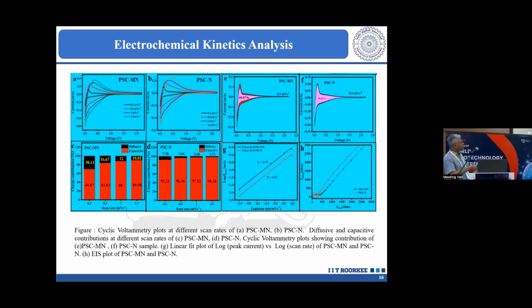So therefore, this is very important to look at. And what is the ratio? If we go from a very low scan rate, we have a good diffusive part, at least the percentage of the diffusive part is 30% or so. When you have a high scan rate, the diffusive part is only 10%. So therefore, it is not getting adequate time to go inside and come back. So this is what to observe. Then we have the plot. This is the plot of the log of rate versus this.